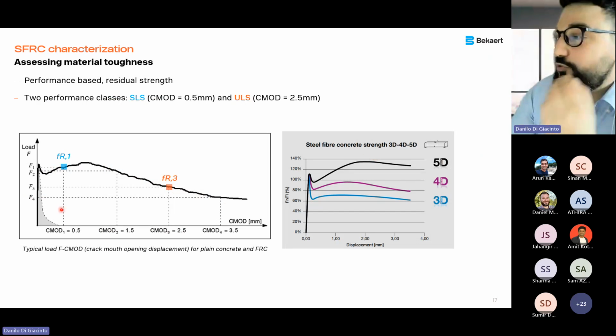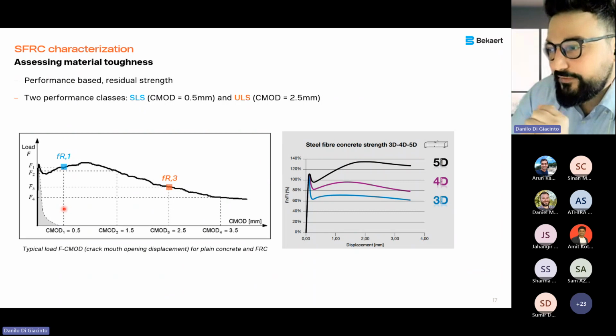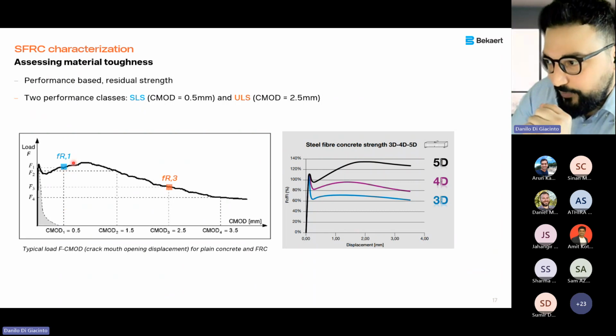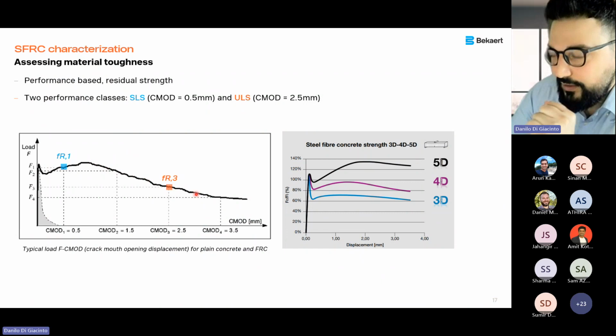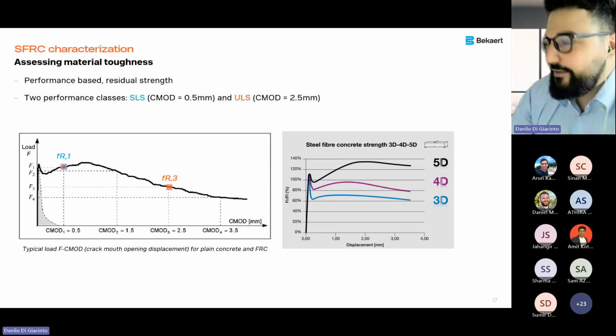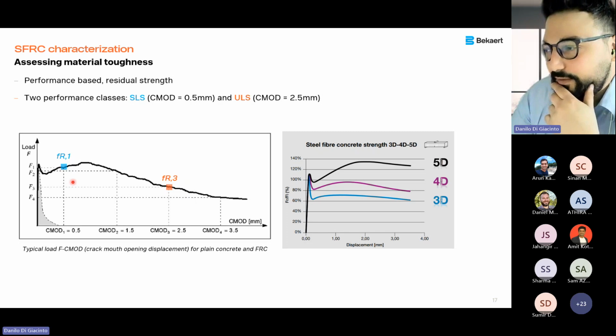And you have, according to the standard, different residual strength values. What are those points? According to the standards, they are residual strength values, so the flexural strength values after the cracking stage. This is the limit of proportionality, which depends basically on the matrix. Then it is standardized. You have FR1 to FR4 values. FR1 is typically associated with the serviceability limit state, while FR3, so 2.5 millimeter CMOD, is associated with the ultimate limit state.